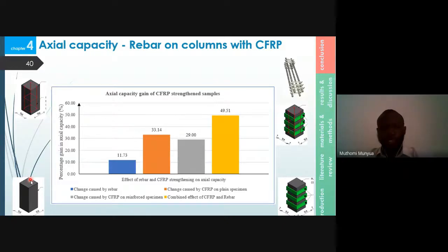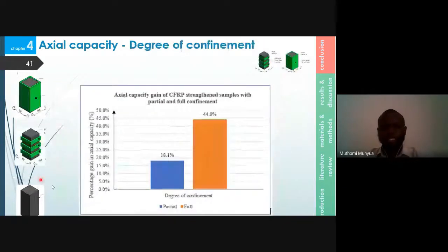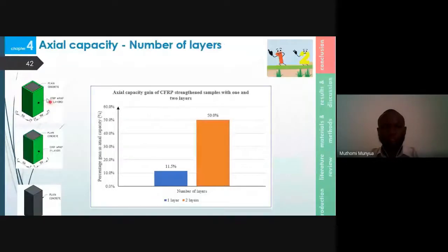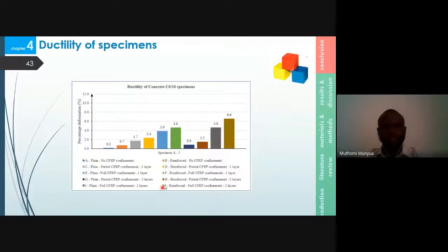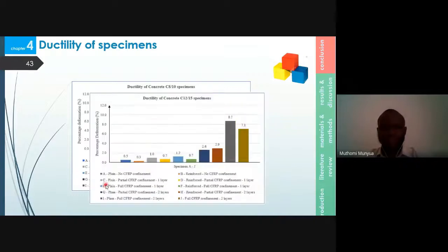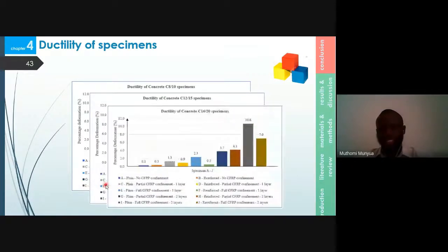In terms of degree of confinement, we found that full confinement was more effective than partial confinement. The same was repeated for number of layers. Two layers were more effective than one. The same process was also repeated for ductility of specimens. The ductility trends are discussed in the write-up here.